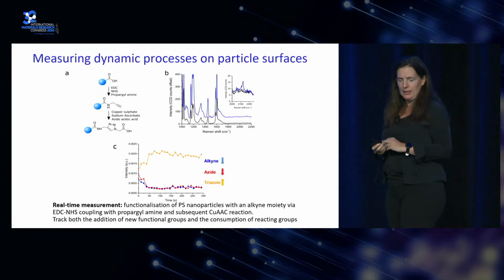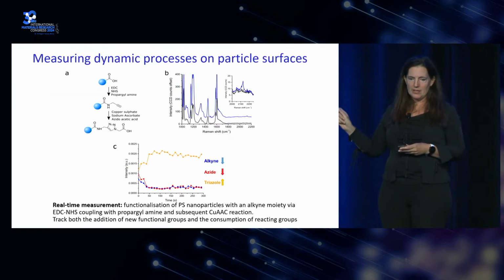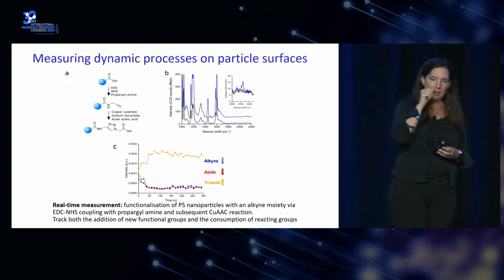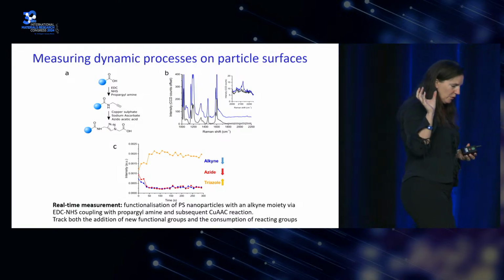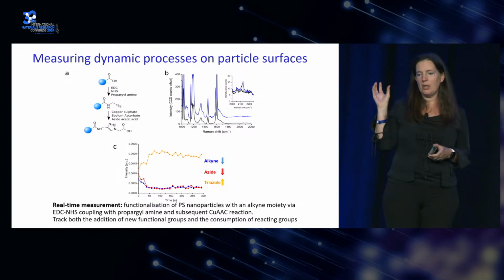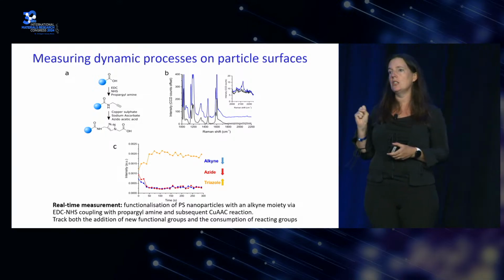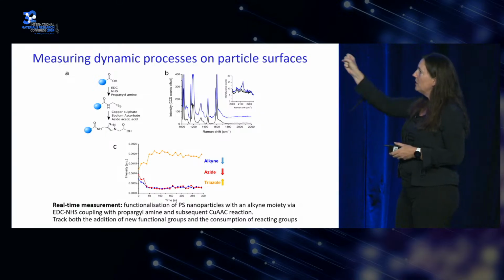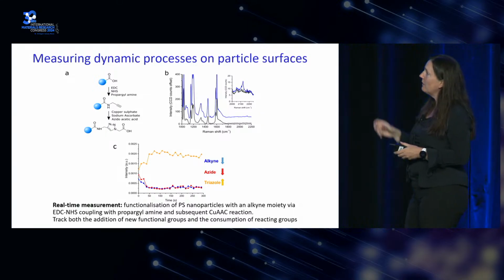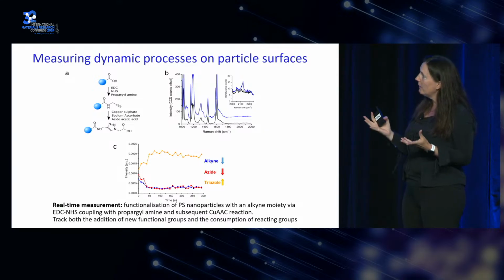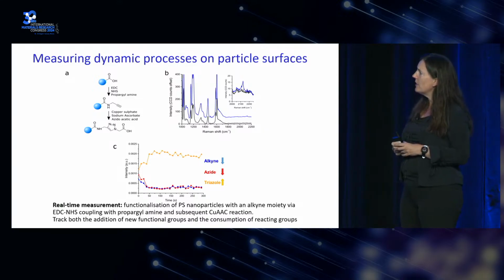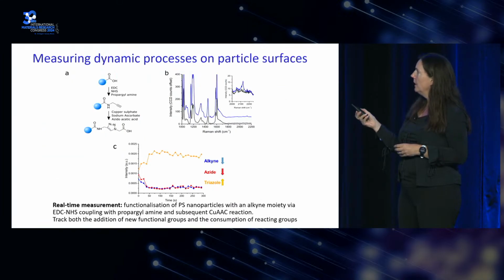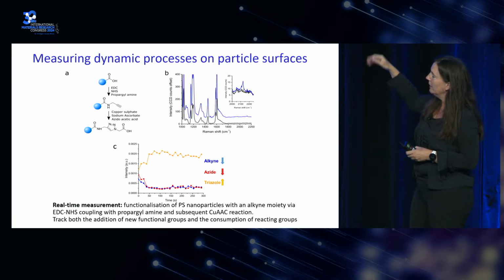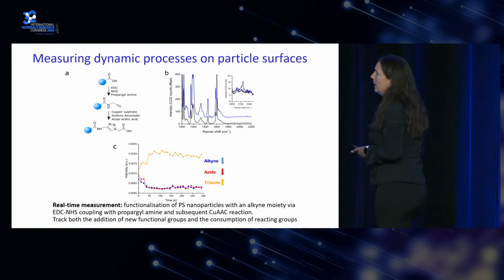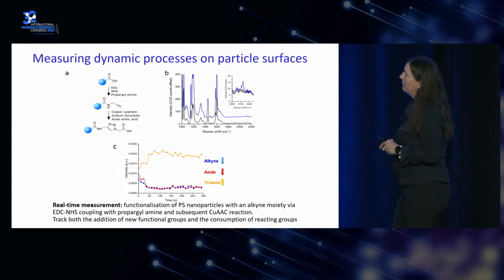So I want to show you this example here, because this was an experiment that I was so excited about, because it was the first time that we trapped a particle and then measured real-time changes in its chemistry. And what we're doing here is, if you look at the top left, we're trapping a polystyrene particle, we're introducing an alkyne moiety, and that leads to a peak in the Raman spectra that's very easy to recognize.